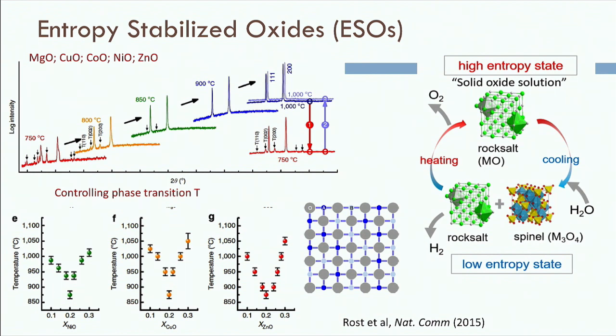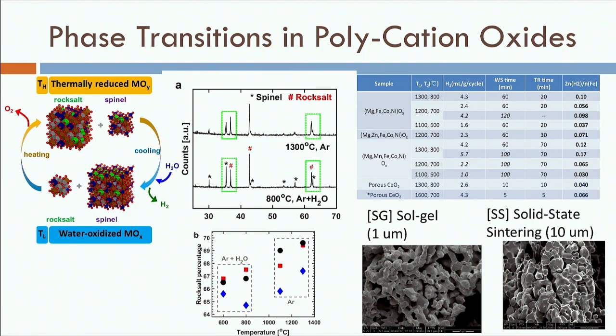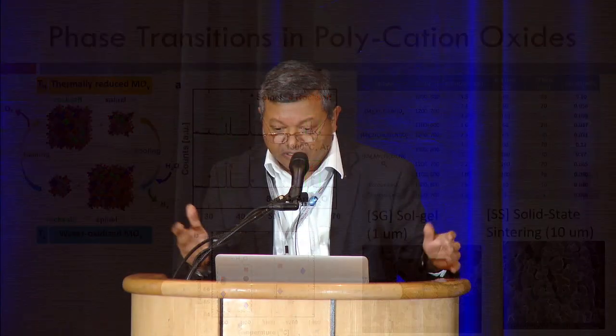Now they discovered this material, but they didn't think about the water splitting part, and so we asked the question, can you use this phase transition for a water splitting reaction to produce hydrogen? And indeed we find a whole class of materials, not just one, a whole class of materials that can split water by a phase transition from a spinel to a rock salt structure, a little bit of spinel. When you go from a spinel to a rock salt, again the oxidation level of the transition metal changes. The question is, how good is it compared to cerium oxide and ferrites that are the high temperature materials? So here's some data.